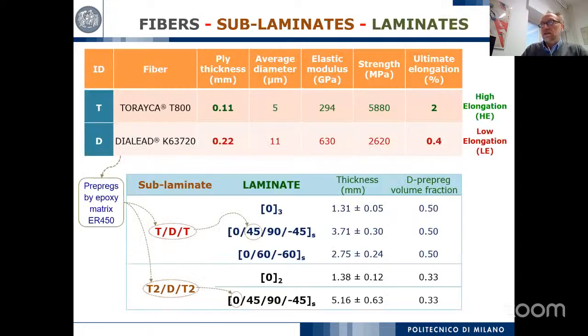As for the material, as I mentioned, we use two different kinds of carbon fiber with different elongation at failure and different elastic modulus. Those are listed there, in which this is the high elongation fiber, this is the low elongation fiber. We also investigated the influence of the sublaminate. So what is a sublaminate? It's a sequence of pre-preg including these two fibers. In this case, we have high elongation, low elongation, high elongation. And this sublaminate is mentioned in the laminate stacking sequence as the orientation. And we also investigated another sublaminate scheme to create unidirectional and quasi-isotropic laminates.